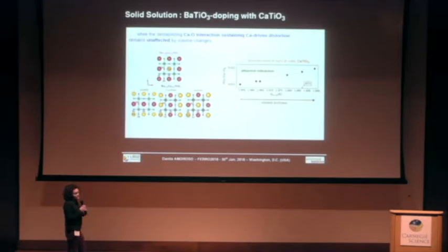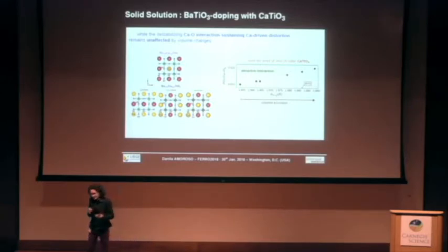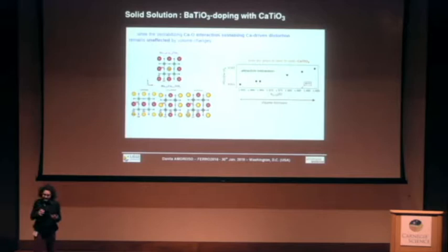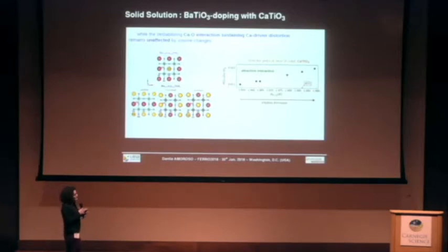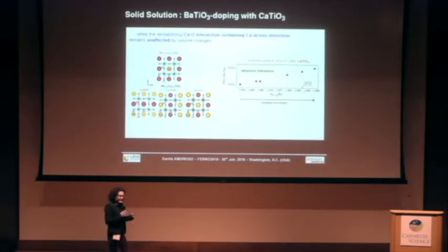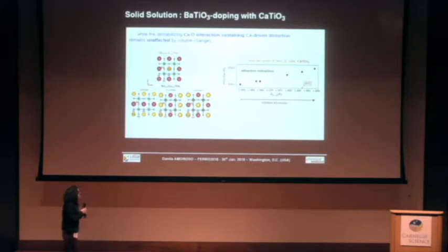But on the other hand, we can consider the fact that calcium titanate will experience an overall increased volume because it's within the matrix of BTO. But this doesn't matter because the interaction between calcium and oxygen stays all the time destabilizing, attractive. And so that means that the calcium-driven mechanism will be a constant in the solid solution. So let's see what is the effect on the energetics of the system.